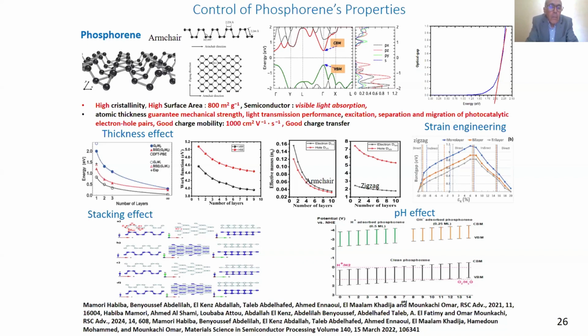To change the stacking, it's easy to do that by some intercalation of ions between the layers. By this intercalation, we can change the stacking from AB, the most stable, to AC, AD, but all these phosphorene stackings are stable, but with different band gaps. Then it is possible to control the band gap by changing the stacking.